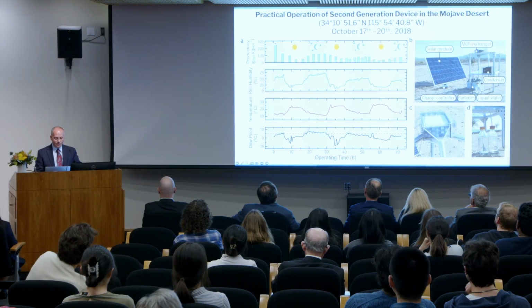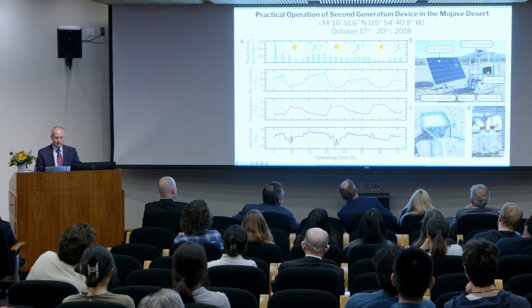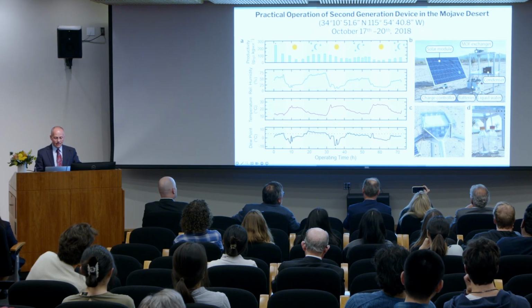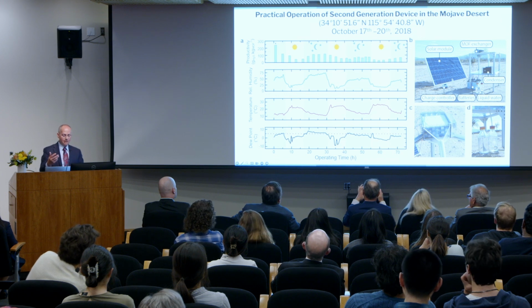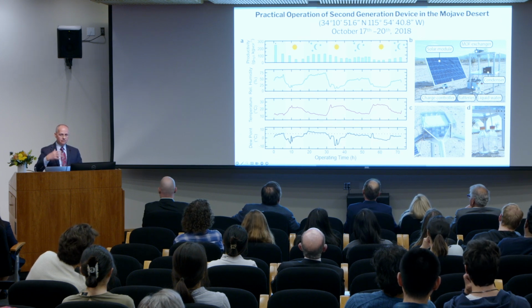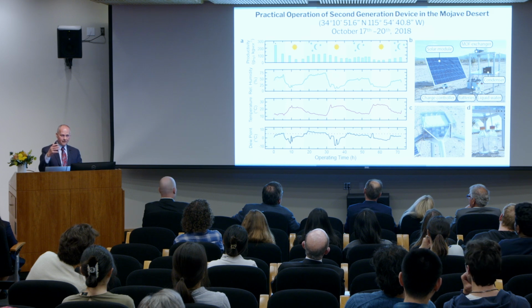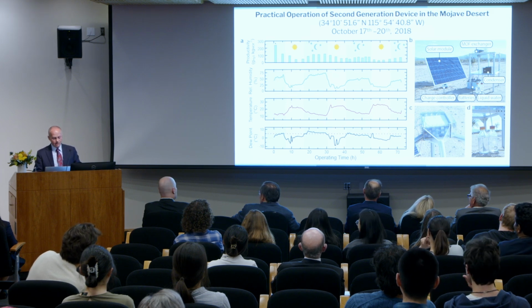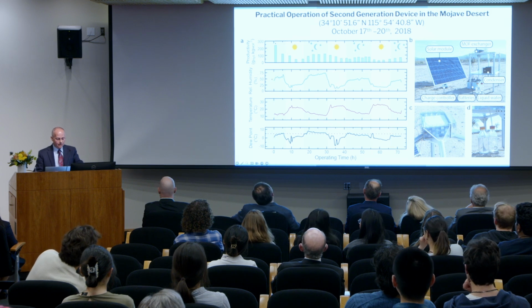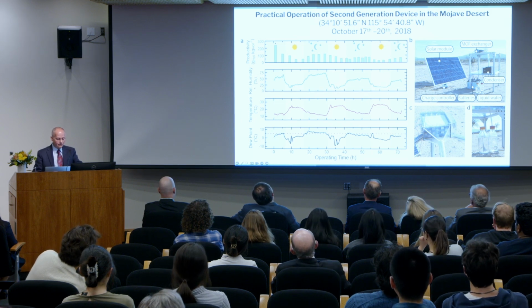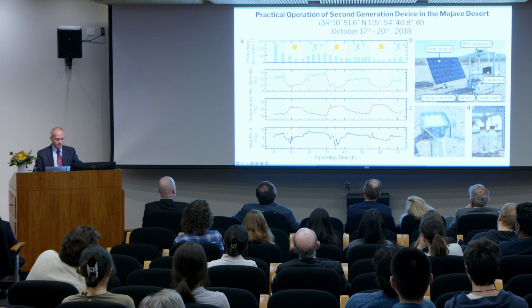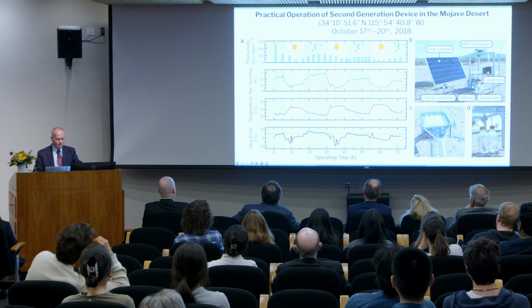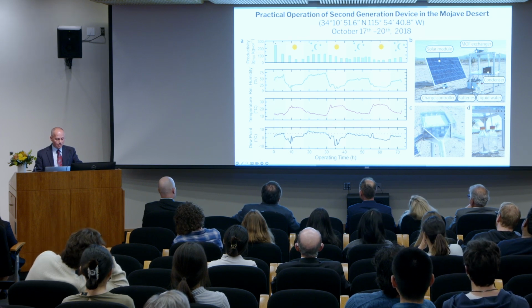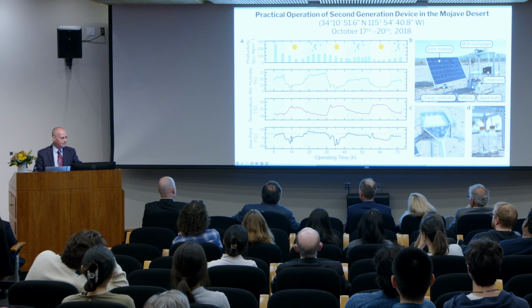And there, they interfaced the module with the solar panel to have enough power for fans to push the air into the MOF, and slight heating of the MOF later to take the water out. But I want to point out these two panels. This is the relative humidity that they measured during the day and night. You can see the humidity can go up to 50%, but it can also go down to even less than 10% relative humidity during the day.